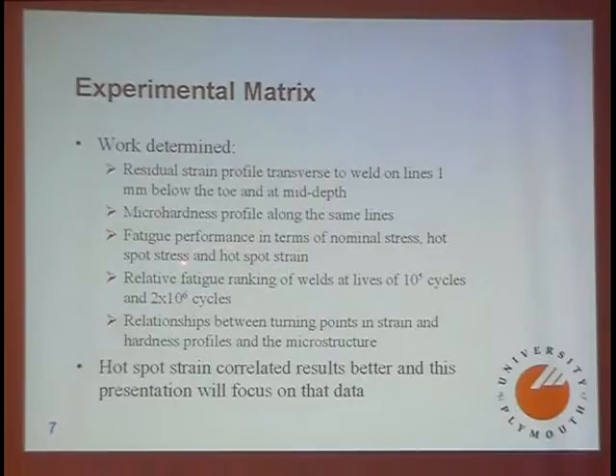And what I was interested in, as I say, is the fatigue ranking of the welds relatively at lives of 100,000 cycles and 2 million cycles. And I'm trying to eventually find relationships between turning points in strain and hardness profiles and the microstructure, and somehow use that information to predict the fatigue ranking.